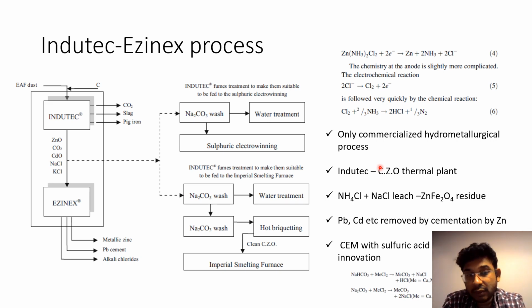So the first thing they did was they took the CZO, or the thing that is obtained from the Indutec process. They leached it with ammonium chloride and sodium chloride leach, right? So the first thing that you need to notice is the pH of these things. It's going to be around 6 to 7. It's going to be buffering around 6 to 7.